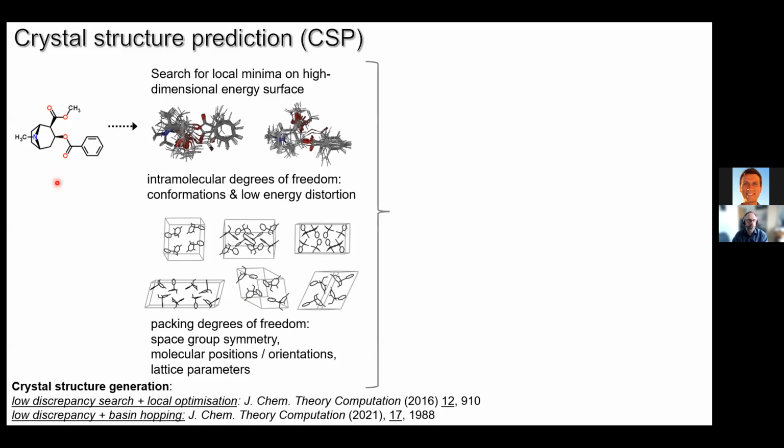The way we do this is we initially have to take a two-dimensional diagram of our molecule and inflate this to a three-dimensional building block of our crystal structures. And we use conformational searching methods for this. We will rotate dihedral angles in the molecule and any other flexible degrees of freedom to come up with how that molecule might look in terms of a three-dimensional object.